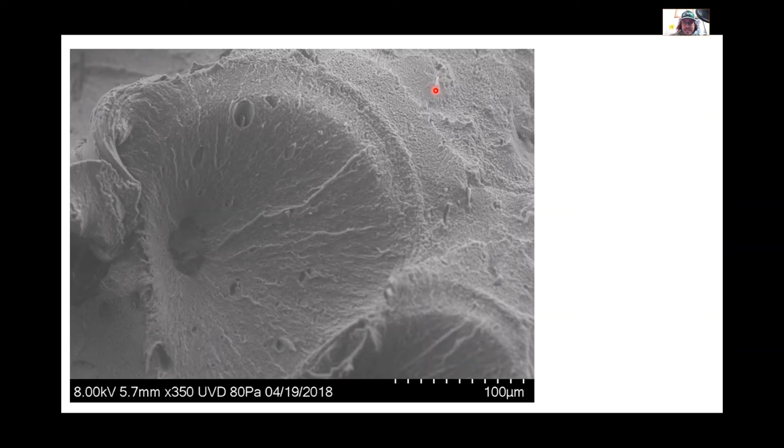There's something else sticking out here, but you almost see this spherical or circular structure around it. And I don't see much plastic deformation here. So I would say this looks pretty plasticky, and this is maybe a mixed mode ductile-brittle fracture, but it was definitely aided by, in fact, we see two intersecting stress fields here. And they're due to the stress concentration of this filler material. So we didn't do a good job making this composite.